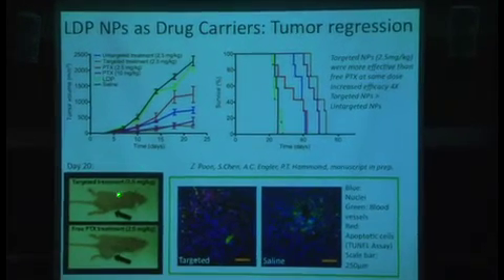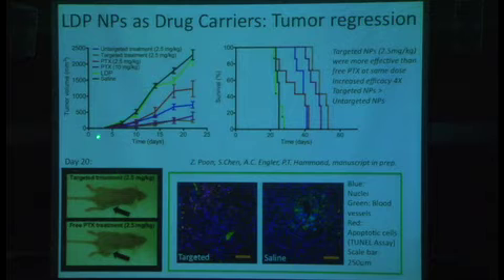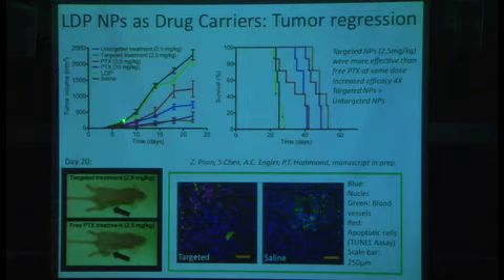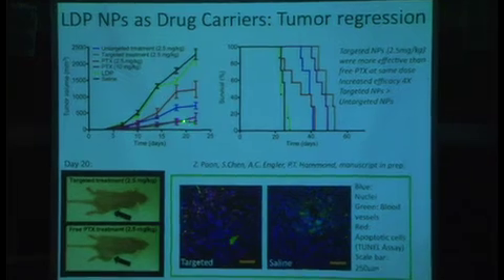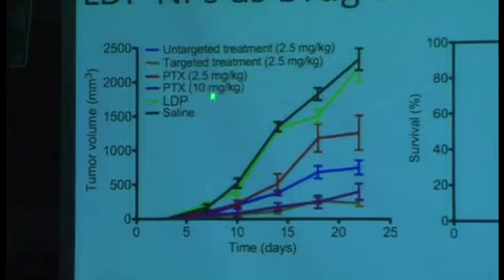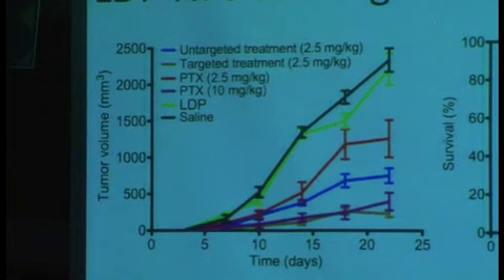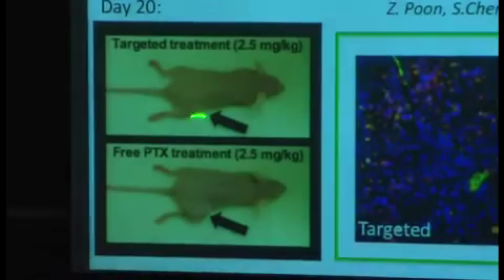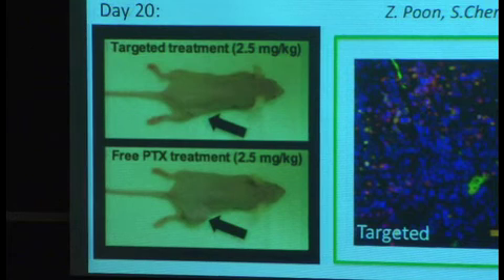We've actually begun to look at these systems with respect to tumor regression when we encapsulate a hydrophobic drug like paclitaxel. In this case, what we see is that compared to saline, and here we have the no treatment group and the saline group, we end up with a very high rate of tumor growth. We compare that to our targeted vehicle, which has 2.5 milligrams per kilogram, and we see a much lower response. Our system, when we just introduce the untargeted treatment, does give us some degree of remediation due to that enhanced permeation and retention effect, but it's much more pronounced when we use our molecularly targeted system. And here you can see a comparison between our targeted system and free paclitaxel administered to the mouse at the same dosage.